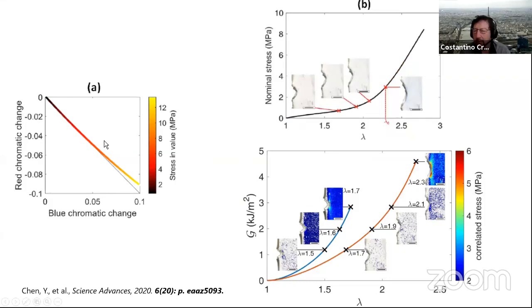Now, what we were interested in is to see whether we could use this uniaxial extension data to actually get some information on a more complex geometry. Because we are interested in fracture, we try to do this with cracks. And if you look at the sample here that shows stress versus stretch, you can see that the sample has a slight change in color.